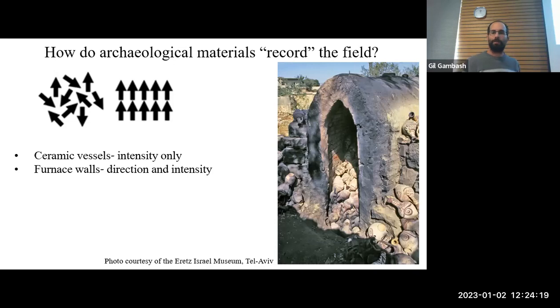and know what that direction and what the intensity was. Now, in order to measure that direction, we need to sample them in the original position in which they cooled down. As I explained, the recording happens not when they are heated, but when they cool down. So if we sample something in the orientation in which it cooled down, then we can reconstruct the direction of the field of the Earth at that time. If we don't have that, we can only reconstruct the intensity.